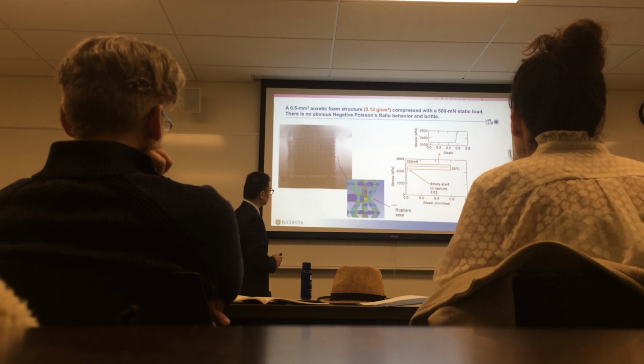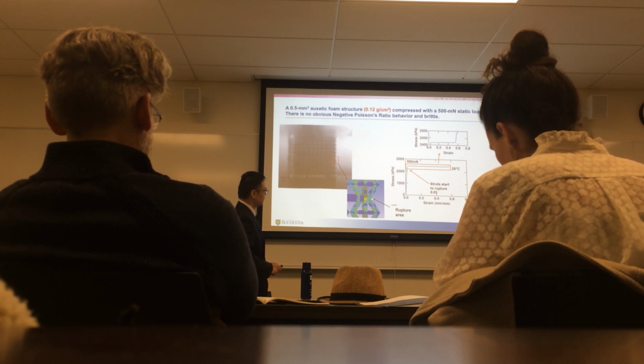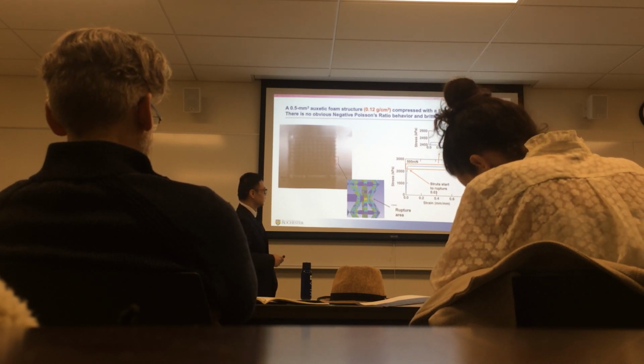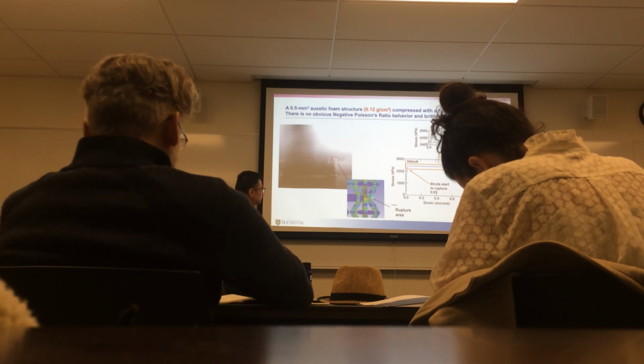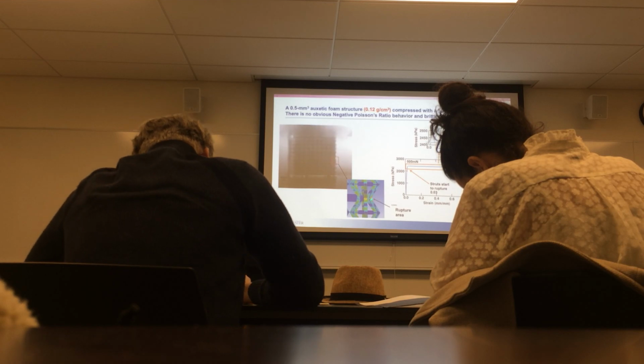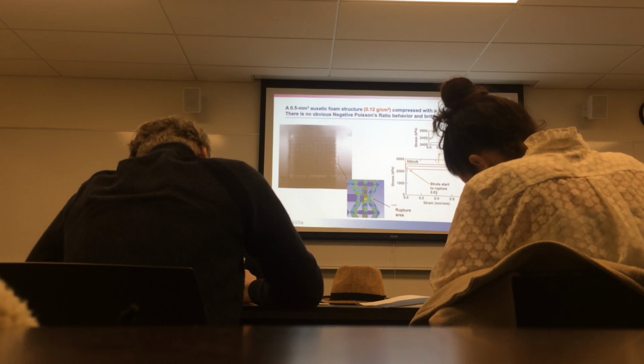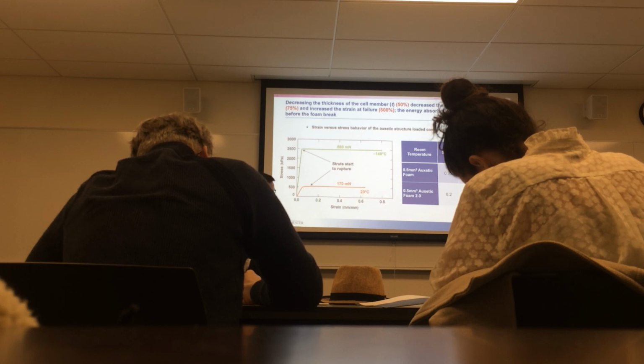Also, using the simulation, I figured out that the corners at the edge hold a lot of stress. So I also enhanced these areas to develop our second generation foam. After we enhanced the corner of the edge and decreased the thickness of the unit cell, we developed our second generation foam and did the test.